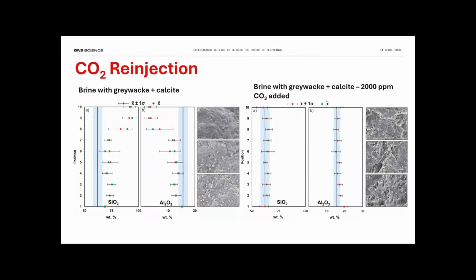So we look at the chemistry. So this is the same type of diagram as I showed you previously. So if we look at the brine with greywacke + calcite, we can see when the fluid enters, we've got higher silica at all positions, and it's all greater than the original rock content, which is this blue line. This blue line is the average rock surface composition. The blue band is plus or minus 1 standard deviation of that composition. And you can see the surface composition of silica. They're all consistently higher than the unreacted rock, and the aluminium concentrations are lower, which means the silica is covering the rock minerals. And you can see the spherulitic precipitates on this rock.